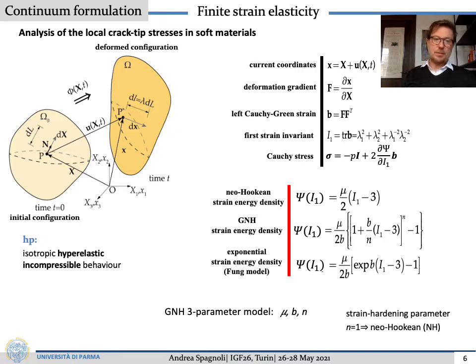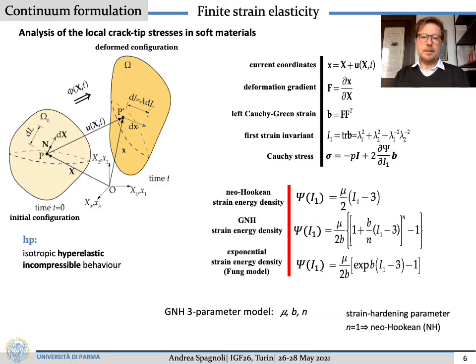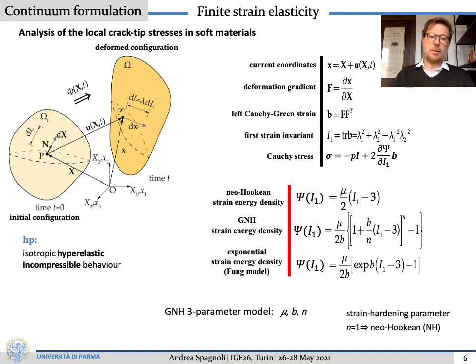We have to work with finite strain elasticity to deal with the problem of soft materials. A distinctive aspect is that the initial configuration is distinct from the deformed configuration, so the coordinates of material points are separate. The deformation gradient governs the kinematics of the problem, and there are different metrics for strain and stress measurements. For instance, the Cauchy stress is the true stress in the deformed configuration. As for the material behavior, we consider an isotropic, hyper-elastic, incompressible behavior, and we deal with neo-Hookean and generalized neo-Hookean materials characterized by a strain energy density. The generalized neo-Hookean material has a parameter N, which is a strain hardening parameter.